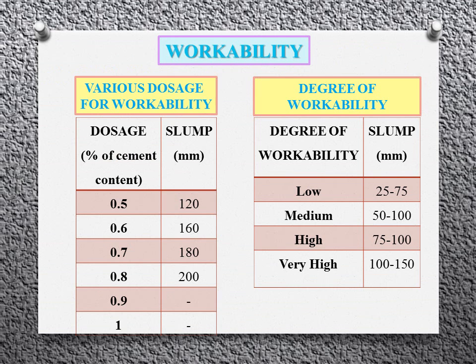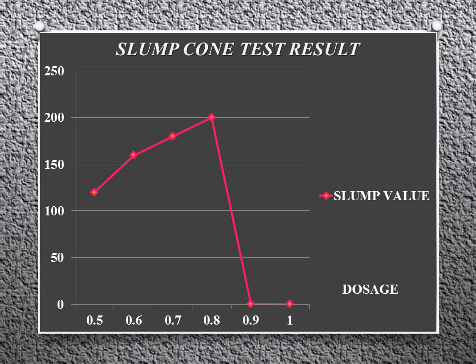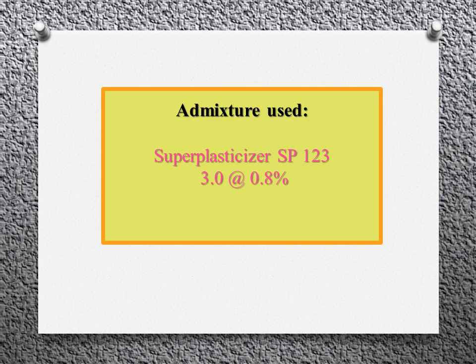The workability test was carried out to find the optimum dosage value for the SNF to be used. Thus, from the values, an optimum dosage of 0.8% of cement content, which gives a very high slump, that is very high workability, is chosen for this experimentation. The slump cone test results are shown in the graph. The admixture used is superplasticizer SP123 at 0.8%.